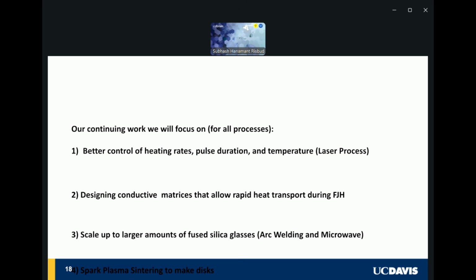So our continuing work, as you know, many of you who are advisors for PhD students, 2 of my students are doing this, and they kind of are exploring different ways. And our continuing work now in the future will focus on better control of heating rates, pulse duration, and temperature for the laser processes, then designing conductive matrices that allow rapid heating during the flash Joule heating. And then, of course, we're scaling up to larger amounts for fused silica glass with arc welding. And more recently, we have been now playing around with trying to put it in a microwave oven and see if microwaves can melt it as long as they're surrounded by alumina and other fiber fabric around it to protect it from the melt.